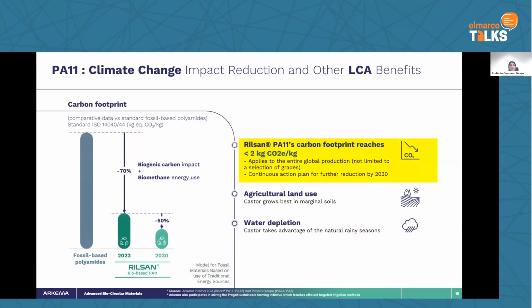Last but not least, of course, when you talk about bio-based polymers, it's important to mention the carbon footprint and where we are with polyamide 11 today. When you compare polyamide 11 to other fossil-based polymers, we have improved these numbers by 70%. So we are 70% below fossil-based polyamides on average. This is due to the biogenic carbon, because it's a bio-based polymer, as we said, and the use of biomethane energy. So this is due to all the decarbonization actions that are put in place by Arkema.